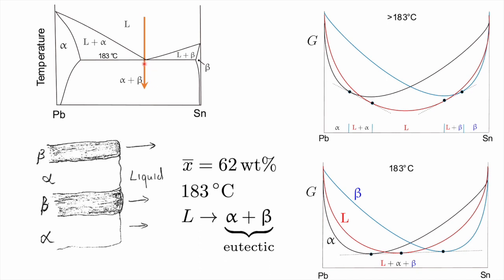And as you cool a little bit below the eutectic temperature, you get beta and alpha growing together from the liquid phase, and this is known as a eutectic mixture of alpha and beta. So liquid decomposes simultaneously into a mixture of alpha and beta. This is the common transformation front between the liquid and the eutectic microstructure here, just below 183 degrees centigrade. And the compositions of the alpha and beta are given by this point here, the alpha in equilibrium with liquid, and the composition of the beta is given by this point here, where beta is in equilibrium with liquid of this composition at the eutectic temperature.